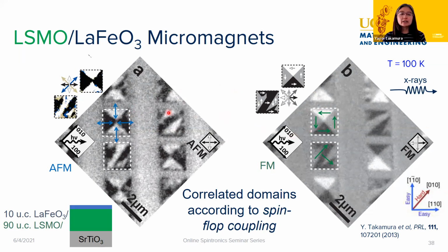So we get the Landau pattern, this bow tie pattern in the antiferromagnetic materials; you can get the Z in the antiferromagnetic domains, right? And so what we did is then do the analysis of the antiferromagnetic domains, and we can actually see that we always get this perpendicular orientation between the antiferromagnetic and ferromagnetic layers, right? So we're getting spin flop coupling, at least regardless of all these domains. That was what we could see from PEEM.